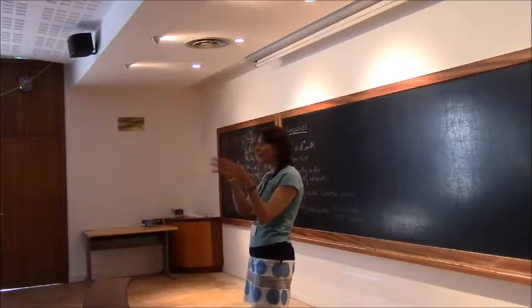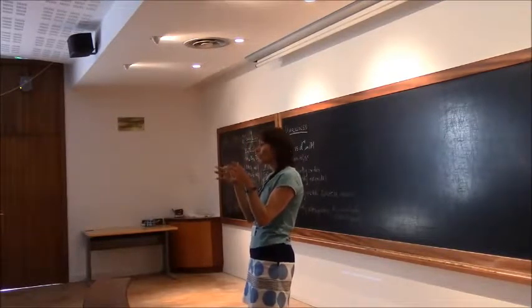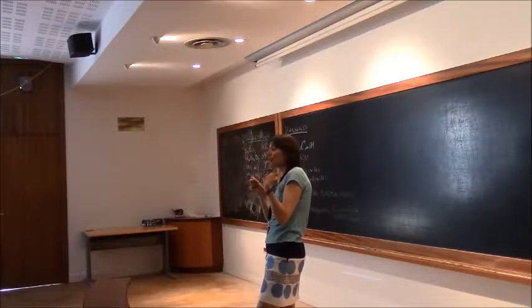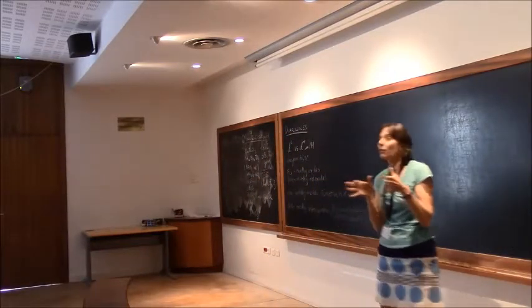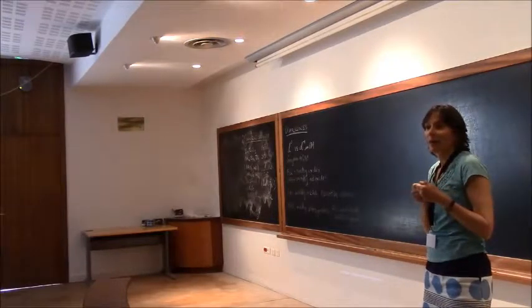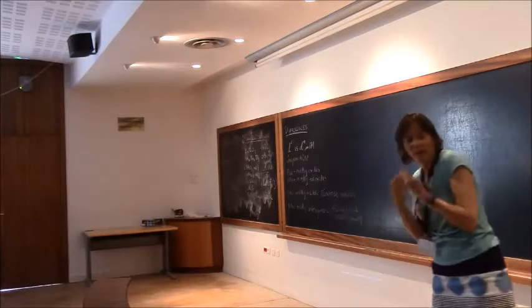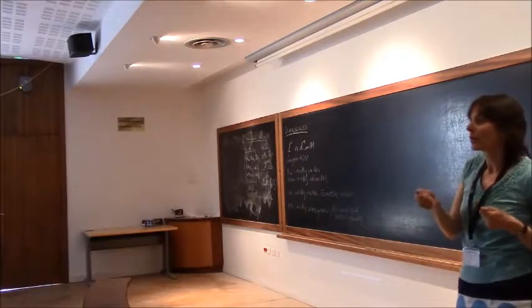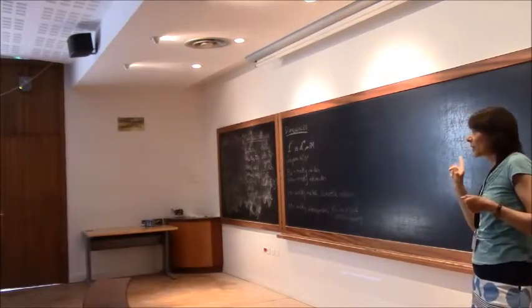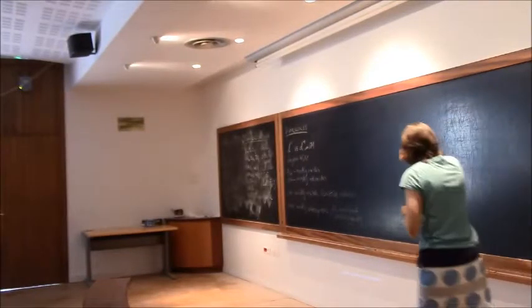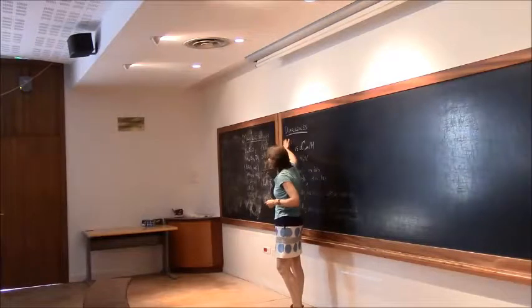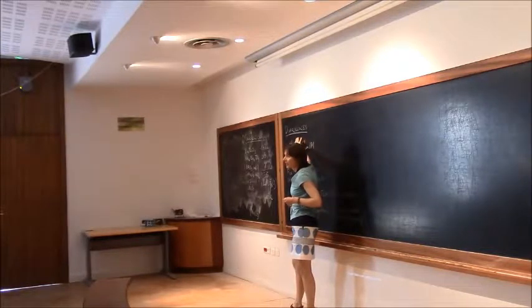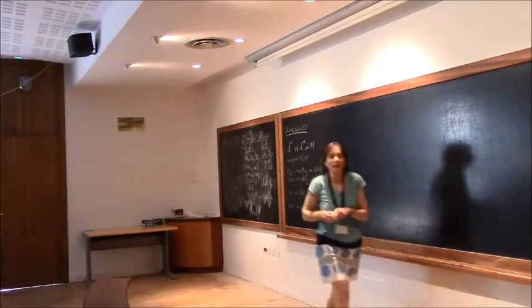We're going to start with the centrosymmetric arrangement of ions and look at whether making a ferroelectric distortion is going to lower or raise the energy. And we'll do that using perturbation theory. We'll take as our zeroth order state a centrosymmetric arrangement of ions, and then see when we make a distortion whether the energy goes up or down. If the energy goes down when we make a polar distortion, then our system wants to be ferroelectric. If the energy goes up, then it wants to not be ferroelectric. And what we'll see is that we can then understand why d0 cations want to be ferroelectric, whereas partially filled d shell cations won't be ferroelectric. So that's where we're headed.